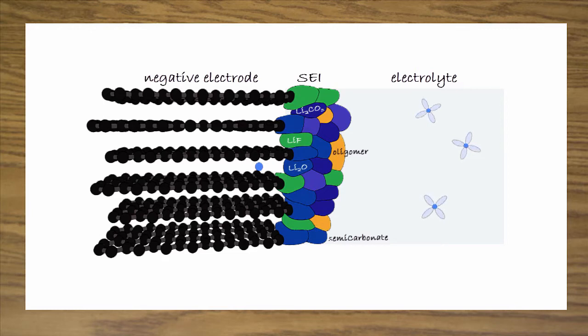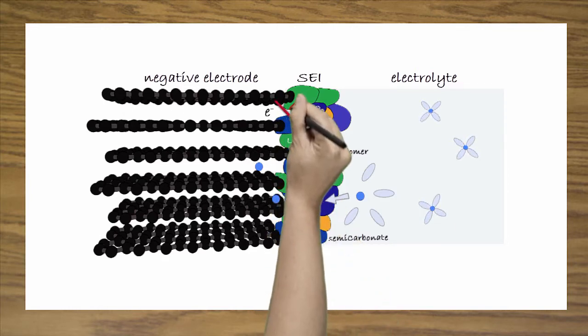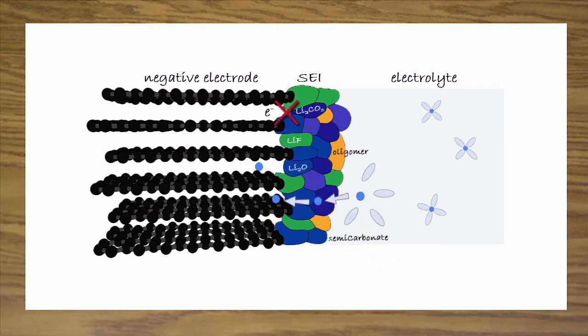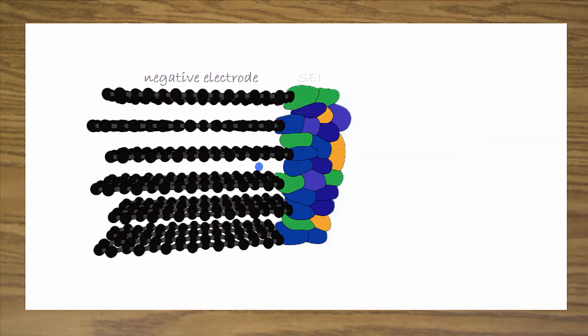This layer serves as a protection on the graphite electrode. The lithium ions can pass through it, but not the electrons, avoiding further degradation of the electrolyte and providing good efficiency of the battery. Many parameters influence the nature of the solid electrolyte interface, such as the composition of the electrolyte, the nature of the electrode, and its surface orientation.